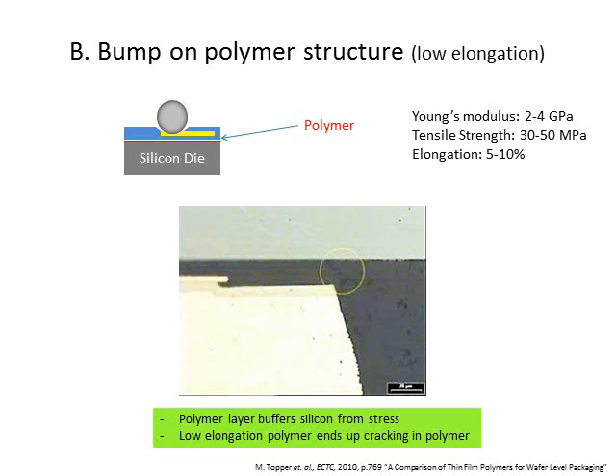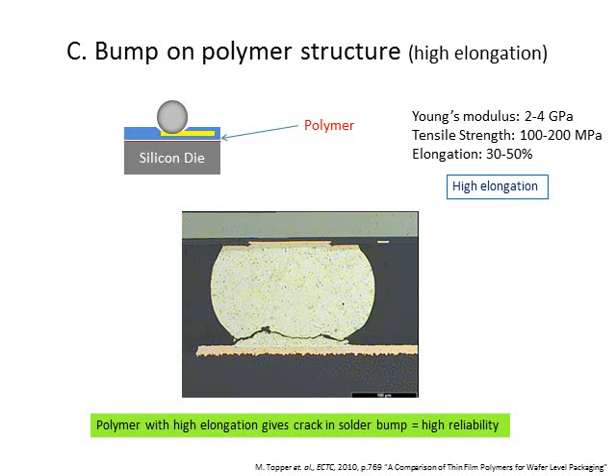However, if the polymer used has relatively low elongation, the cracking mode happens inside of the polymer. By selecting a polymer with much higher elongation, we can avoid the cracking in the polymer, and the cracking mode has changed to the inside of the solder bump. And this is a well-known indication of higher reliability.